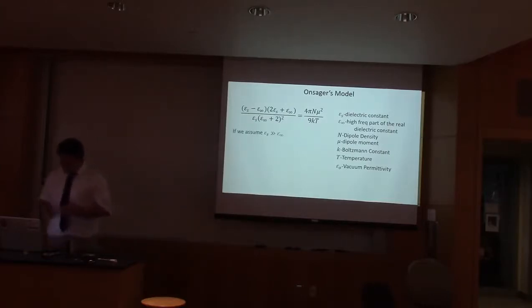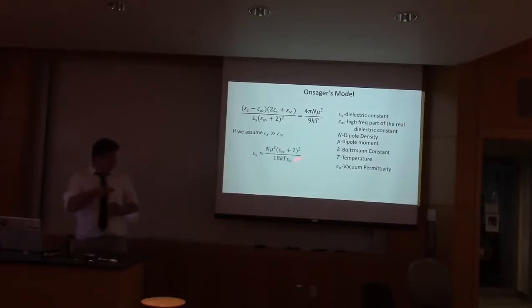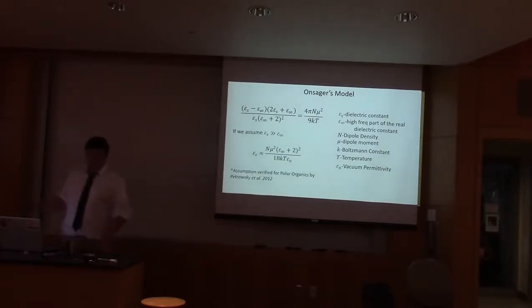If we do make the assumption that the dielectric constant is significantly larger than the high frequency part of the real dielectric constant, we can come down to this statement saying that the dielectric constant is approximately equal to the dipole density divided by temperature times a bunch of these constants that we have here. This assumption was verified for polar organic liquids by Petrowski et al. in the scope of that paper that made the original assumption.